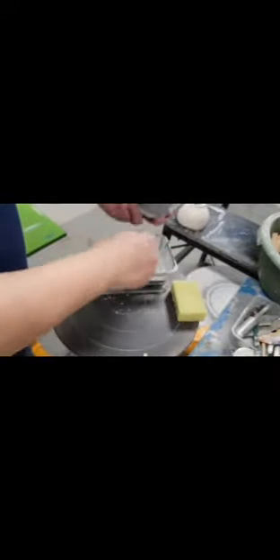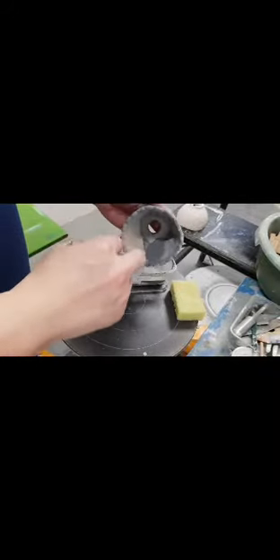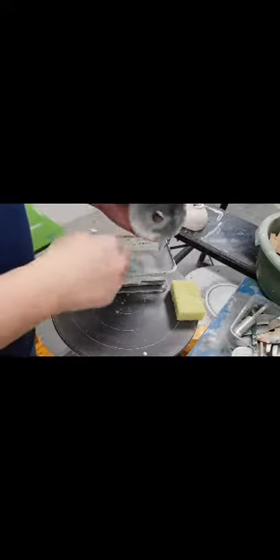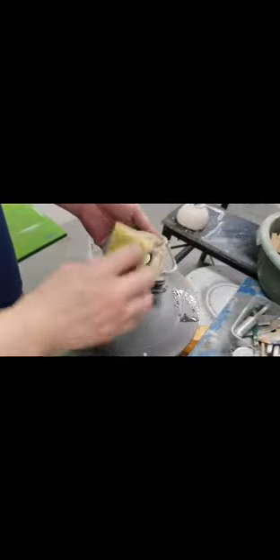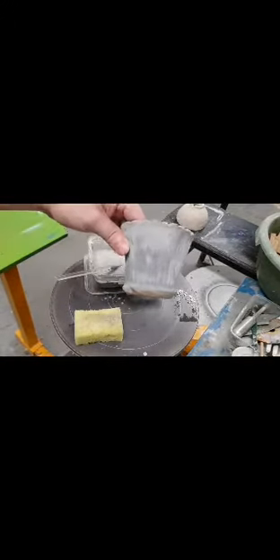Now, I'm also adding copper oxide into the raku glaze, which will help to get the many colors and lusters of the copper, since copper is very sensitive to atmospheric changes. In the raku process, there will be a heavy post reduction after the firing, and that would usually make the whole pot lustrous and almost metallic, from copper metal to greenish to golden. I add around 15 to 20% of copper oxide into the glaze. If you can measure it dry, it'll be better, but it's around there. Or in liquid form, you add about 15 to 20% of copper oxide or copper carbonate in there.